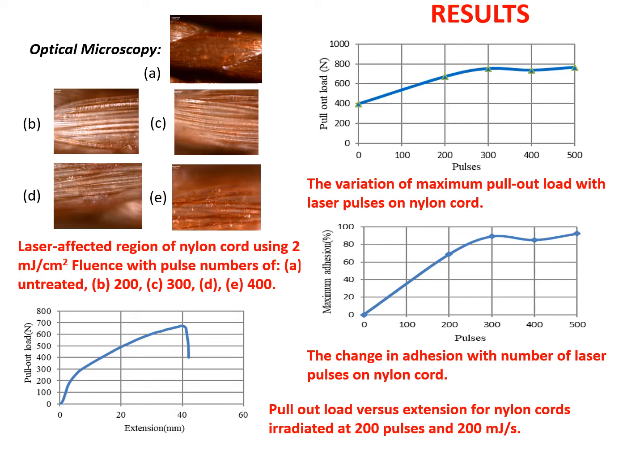The surface conditions, as seen by optical microscopy, are depicted on the upper left under different numbers of pulses. The waviness and ripple structure increases with the number of pulses. And a typical pull-out load versus extension curve is shown on the lower left. This was obtained by using 200 pulses with a fluence of 200 millijoule per square centimeter. The variation of pull-out load and maximum adhesion are shown on the right as functions of pulses.